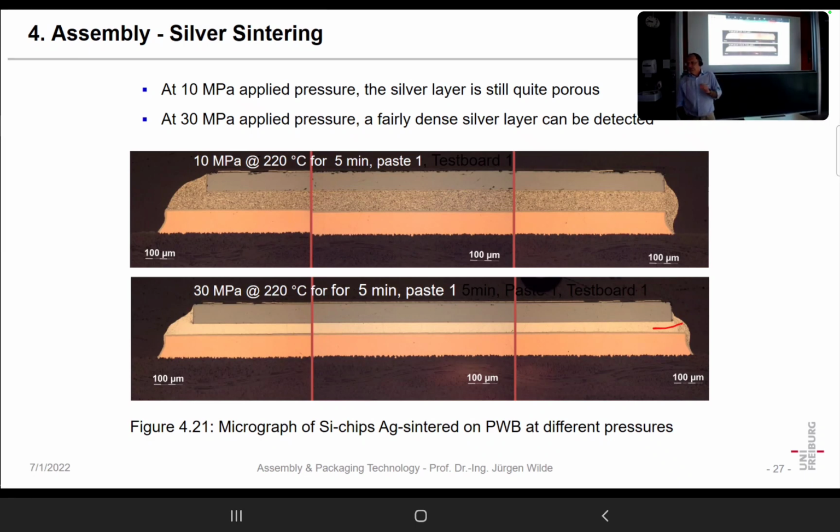A low temperature for us here, let's start with 300. The second is, if you still want to decrease it, you must address chemistry. And chemistry means you have some activators which improve the rate of diffusion of the silver in that sintering process. And that was done by, you could say, industry.